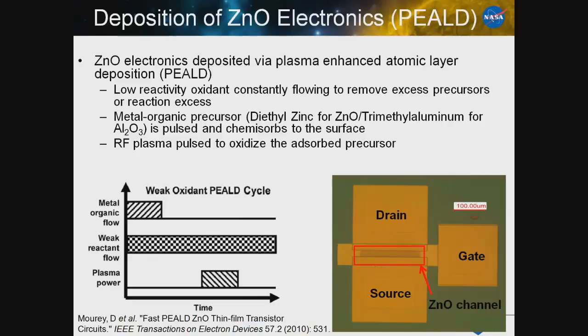And so we've looked at being able to prepare zinc oxide thin film transistors on the adjustable optics. The zinc oxide itself is deposited via a plasma-enhanced atomic layer deposition, where we would, for example, have a pulse of the zinc come in, we flow continuously a weak oxidant, and then we pulse a plasma periodically to drive the decomposition reaction for that material. And I show here, we also deposit the dielectric, which we're currently using aluminum oxide, by the same generic approach. And you see here a fabricated zinc oxide thin film transistor.